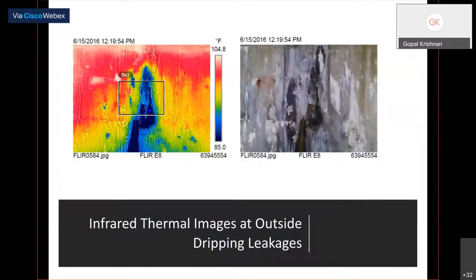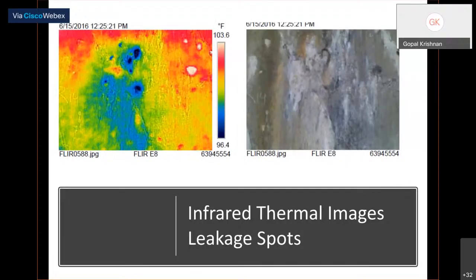So when we use the thermal image, we can see the area, the water intensity, or the source of the leakage very accurately. That is the first point. In some places we observed not only moisture, but water dripping continuously. So both can be identified, and we can be assured that this is a problem leakage spot.